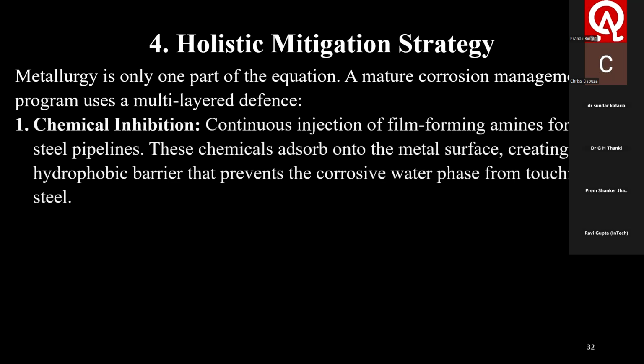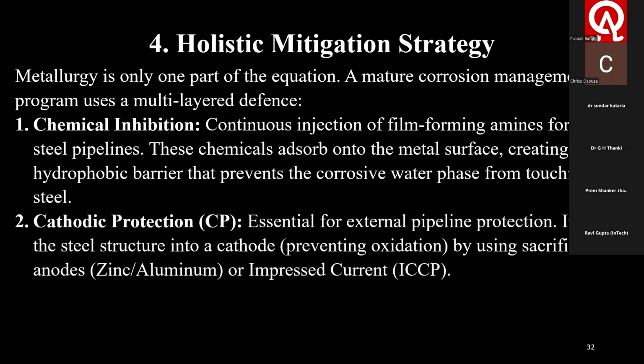Chemical inhibition: continuous injection of film-forming amines for carbon steel pipelines. These chemicals adsorb onto the metal surface, creating a hydrophobic barrier that prevents the corrosive water phase from touching the steel. Second comes cathodic protection, essential for external pipeline protection. It turns the steel structure into a cathode, that means preventing oxidation by using sacrificial anodes like zinc and aluminum, or impressed current, ICCP.